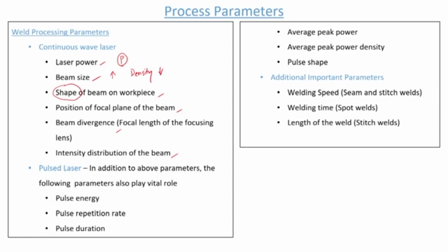If you are considering the circular laser beam interaction, the circular area of the laser beam, then it has been noticed that the shape of the weld bead is very similar to an inverted bell. The inverted bell shape is considered as the opposite or the reverse image of the Gaussian or the normal distribution or the bell shape.